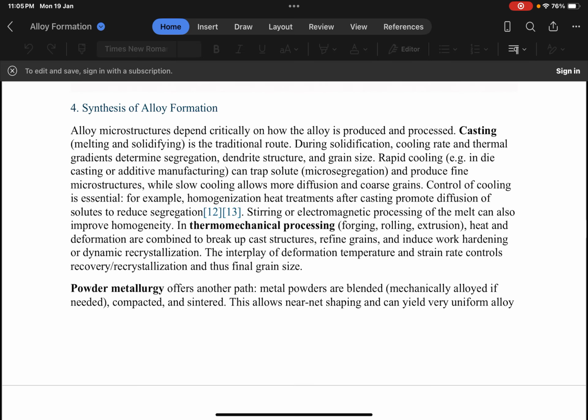The second method is thermomechanical processing, that is forging, rolling, extrusion. Heat and deformation are combined to break up cast structures, refine grains, and induce work hardening or dynamic recrystallization. The interplay of deformation, temperature, and strain rate controls recovery and recrystallization and thus final grain size.